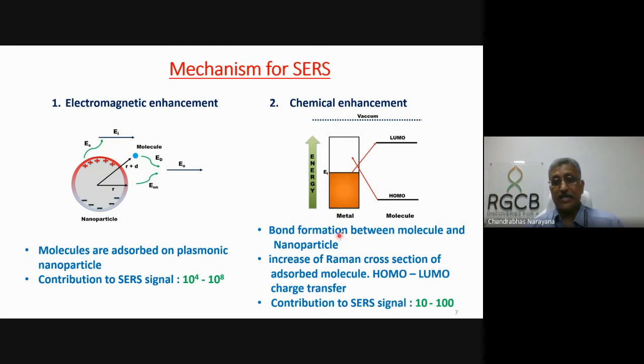Now, what other thing happens is that if your molecule actually binds with a nanoparticle, then the Fermi level of the metal actually matches with the HOMO-LUMO mid gap. And hence you get additional channels for the electrons to go from HOMO to LUMO, and that increases the possibility of many electrons going into the HOMO-LUMO gap, and that means you will have more Raman signal coming from it. And this is called chemical enhancement, and that comes to about 10 to the power of 1 to 10 to the power of 2. So you can actually have around 10 to the power of 6 to 10 to the power of 10 enhancement in general. And in some cases, if you have resonance, then you can go up to 10 to the power of 14. And that is good enough to give single molecular detection also. So these are possible in SERS.